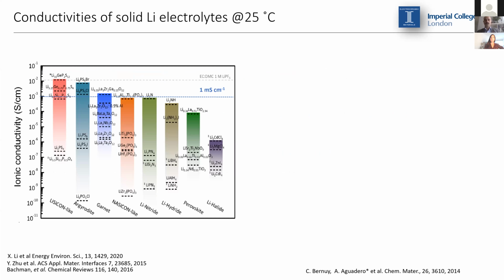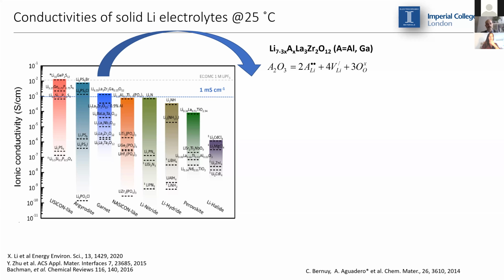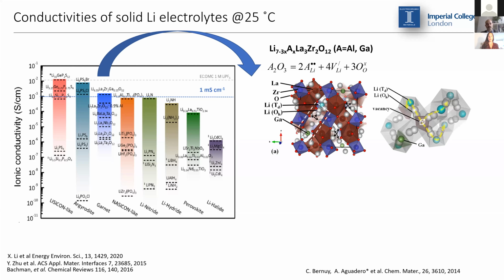In the last few years, there has been a lot of research in this area, and we have represented here 3 families of electrolytes that have surpassed this 1 millisiemens per centimeter that is required for technological applications. In this sense, the sulfides have presented the highest conductivity, and in the case of the oxides, we have developed the garnet electrolyte that has performed with the highest lithium conductivity.